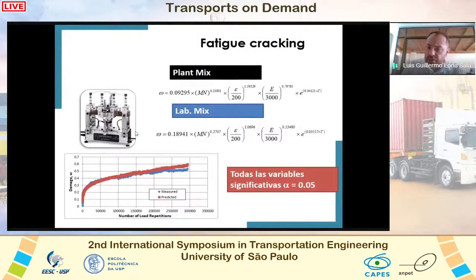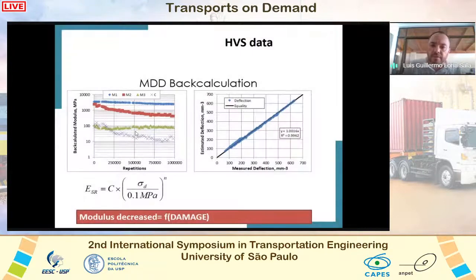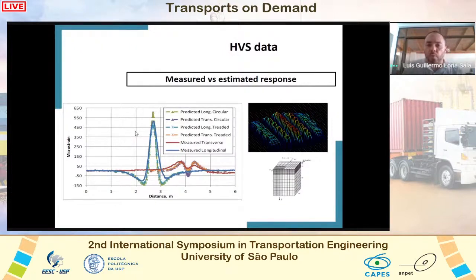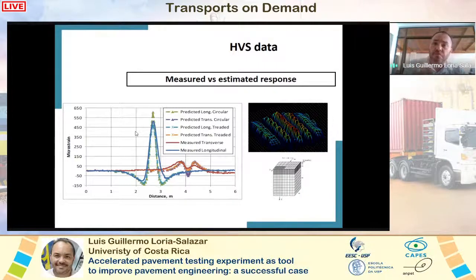So we put one on top of the other for the plant mix and for the lab mix, and we developed a calibration using the same idea that I already showed you. We performed this analysis that I'm showing you right now, just to be sure that the moduli that we calibrated for the various layers were good. For example, in this case, this is the strain measurement at the bottom of the HMA. So we tried to see if the moduli that we calibrated were good enough to produce the same strain signal. So we said, okay, we have a very good match between the theoretical strain signal and the real strain signal. What was the idea of that? To know that we do a very good back calculation of the various layers.